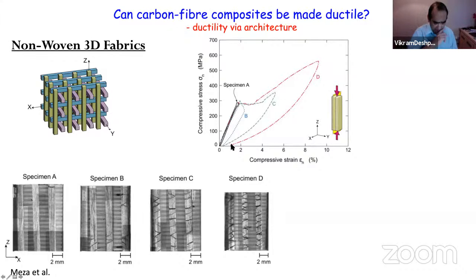After you've unloaded, we put it in a microscope to have a look at it, basically. So what you can see is in specimen A, there is some damage here, but not much. Specimen B, you can see these are those Z direction toes. You can see some kink bands. In specimen C, you can see more kink bands. In specimen D, you can see even more kink bands.